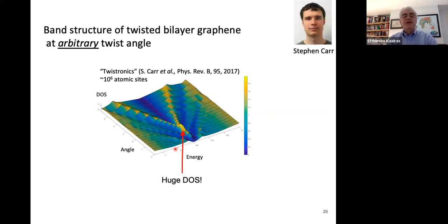So now I'm plotting here the density of states on the vertical axis, also color-coded, yellow being highest, as a function of the twist angle on the y-axis, and as a function of the energy on the x-axis. So the zero angle results shown here correspond to the density of states of two layers of graphene untwisted, just on top of each other. And as you change the twist value, you get these very interesting effects. And in this range, you get a very high density of states, which is really quite interesting and exciting.